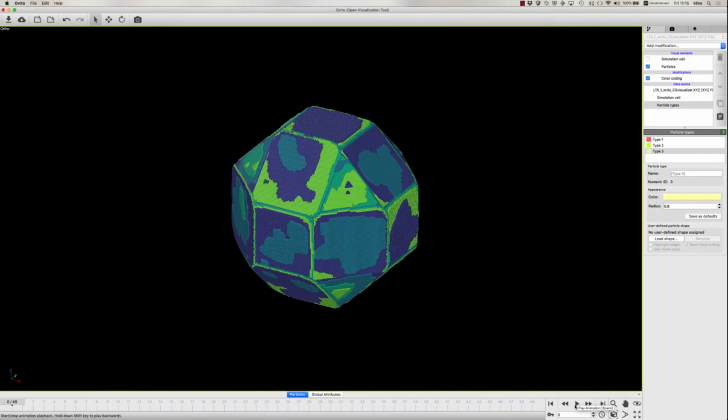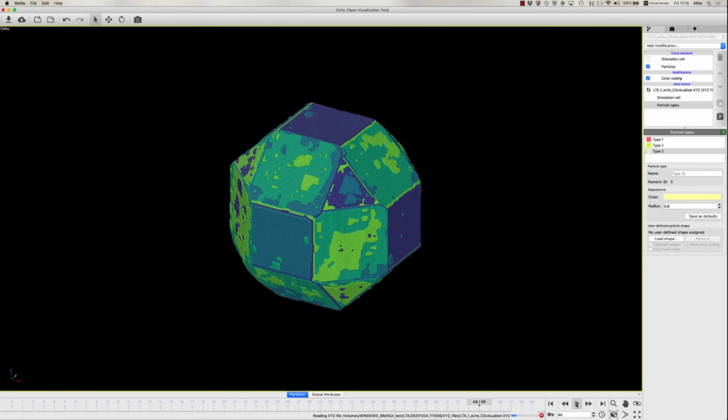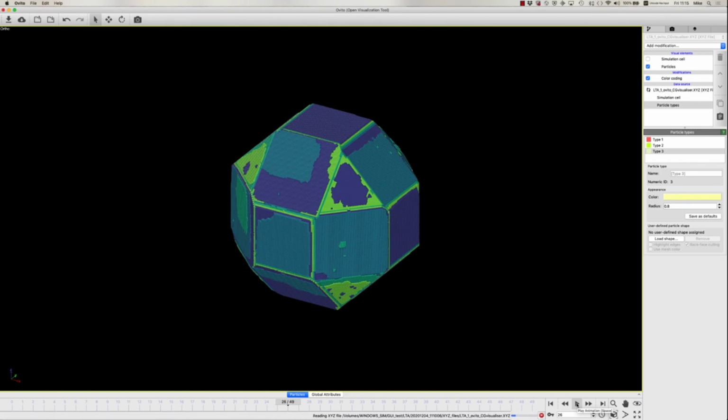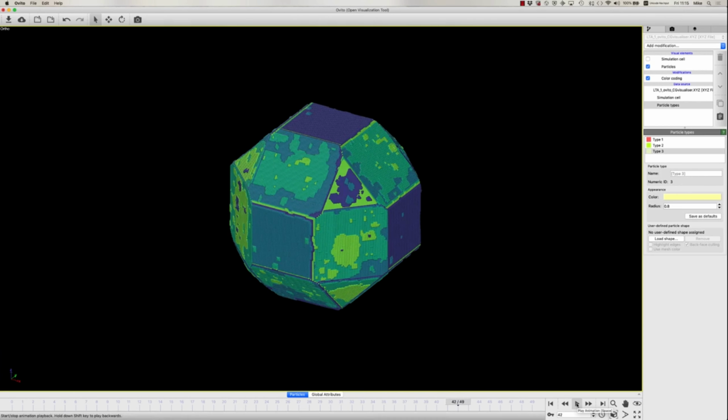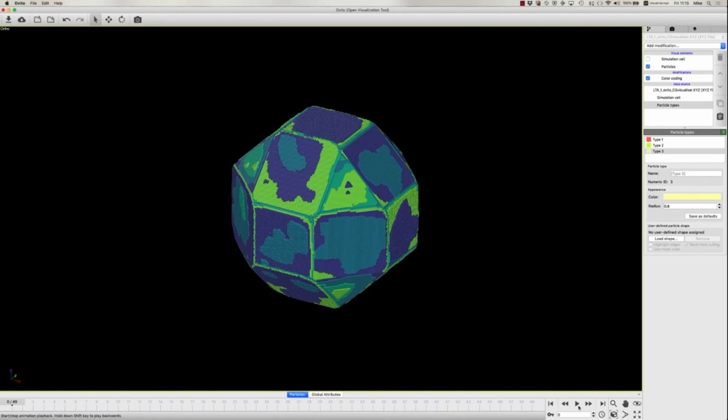Now we can go and look at the simulation in Ovito, which is here, and if we run through the movie, we go through the different levels of supersaturation. So let's run through the movie, I'll run through it again. I'll just run this slightly more slowly so that we can see what is happening. So I go right back to the beginning and just do it frame by frame from the beginning. At the beginning you've got nucleation on the 111 facets, that's at 1 kilocalorie per mole.